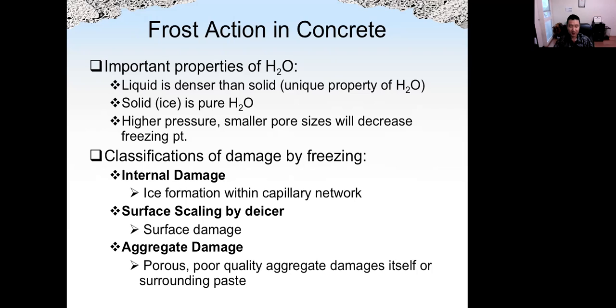The third property of H2O is if we increase the pressure on the ice, and the smaller pores will reduce the freezing point of water. So that means if we increase the pressure on ice, for example, we step on ice, then the freezing point will be lower. So that means the ice may be melted with higher pressure. And also the water in smaller pores will have a lower freezing point. So that's another important property for water.